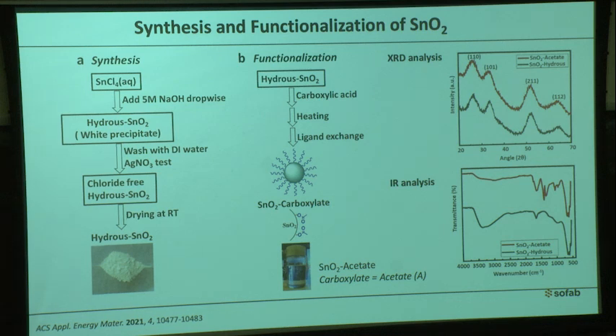From our previous discussion, to deposit metal oxide directly on top of the perovskite, we need pre-synthesized metal oxide. I synthesized tin oxide by neutralizing tin salt with a base, and this is the tin oxide powder, called hydrous tin oxide. This tin oxide was dried at room temperature, meaning it was dried at normal condition but still contains a lot of water.